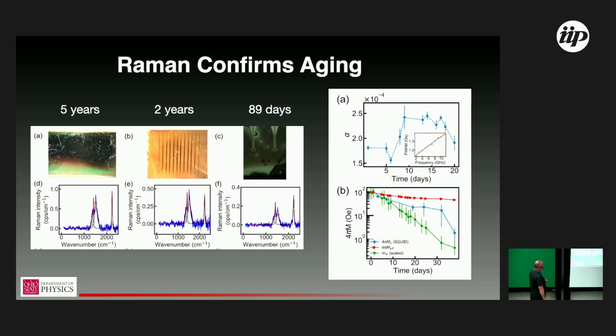And when I say promise for future stability, this is a sample we had sitting in our dry box for 5 years. And you can see it started to oxidize a bit from the edge, but sort of self-limited. The black at the top is the color of as-grown VTe2. And that sample looks pretty much the same as when we grew it. The magnetism has degraded, but the Raman character has not. So there's some structural transformation that's happening over time, and you can see stability, sort of years, days, it basically all does the same thing.